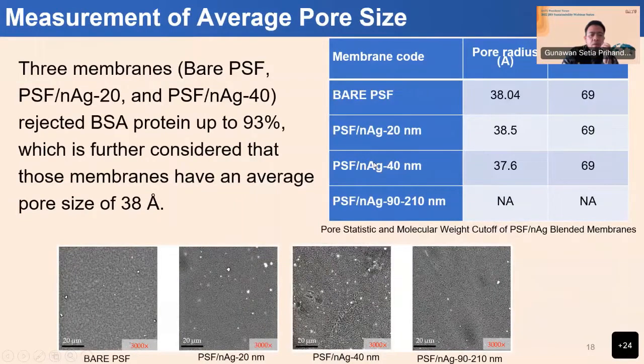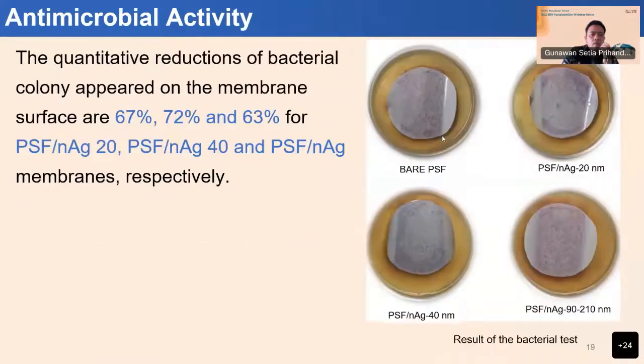For the process, we can use this based on what kind of proteins are rejected by the membrane. So based on this result, we can calculate the protein that can be rejected, like BSA. Based on this, the pore size is around 69, so you can use a 69 molecular weight cutoff, and the pore size is around 38 Angstrom, around 0.0038 micrometers.